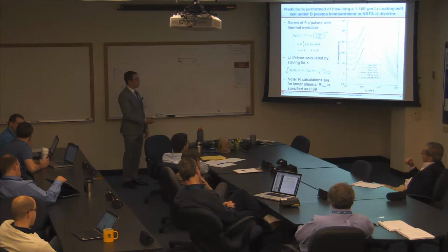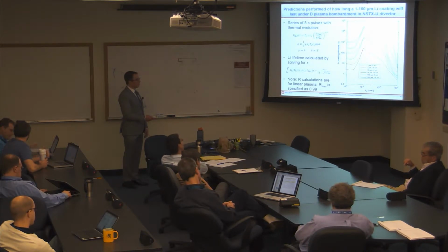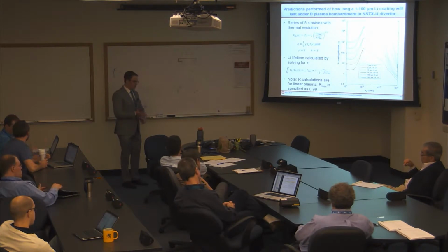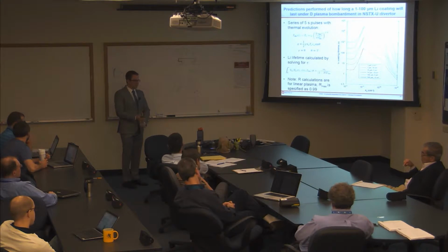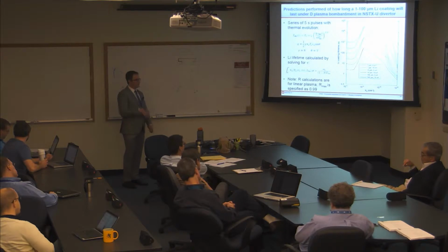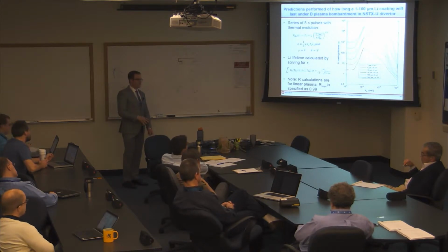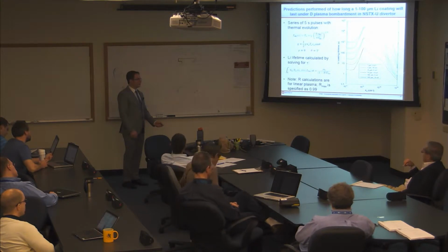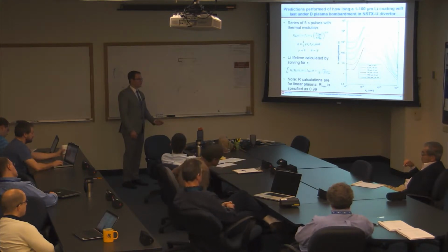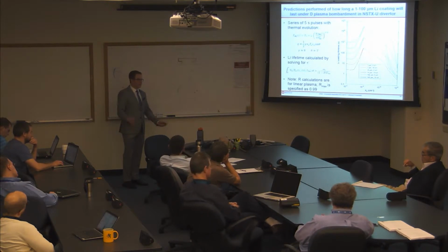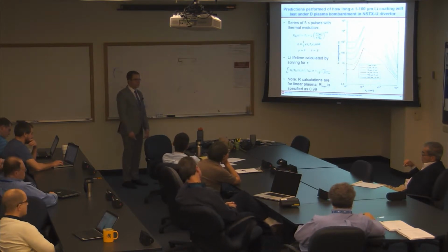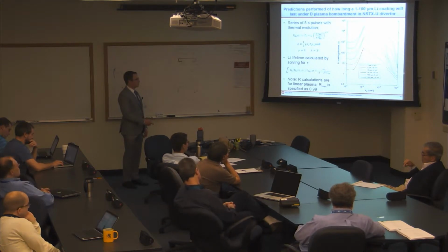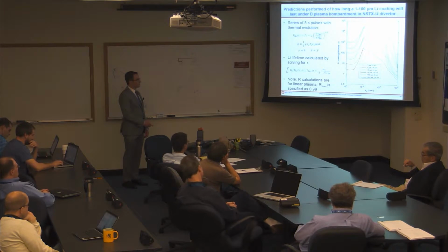And then up here, at this point the PFCs are starting to get pretty hot, and so you have evaporation occurring also. It's a balance between whether the lithium layer can become saturated with deuterium before it fully depletes. Because if it gets saturated with deuterium before it depletes, then the erosion rate all of a sudden goes way down. But if you're way up here where the erosion rate is just too fast, then the lithium layer is just gone before you can get significant saturation of deuterium in it. So that's why up here it starts to get nonlinear with density and temperature.